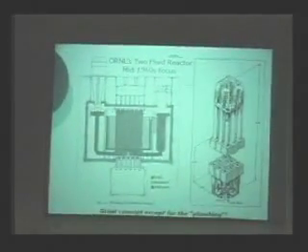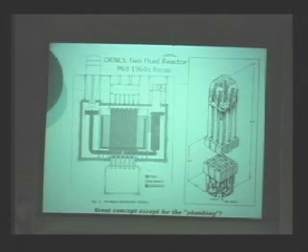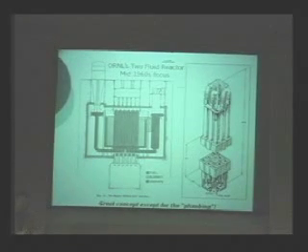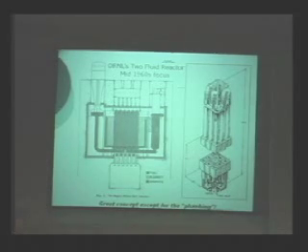There's also a one-and-a-half fluid design — sort of a mix of both types with a mixed salt in the central core region and a solid blanket grid. Oak Ridge's two-fluid work through most of the 1960s involved interlacing the two fluids through very complicated graphite plumbing — tubes of graphite carrying fuel salt, with blanket salt between them. That graphite under irradiation first shrinks and then swells, creating a real plumbing nightmare, and that's really what killed that approach.